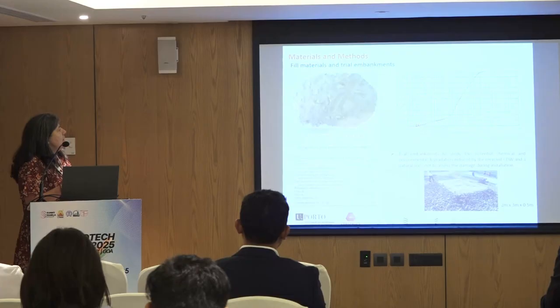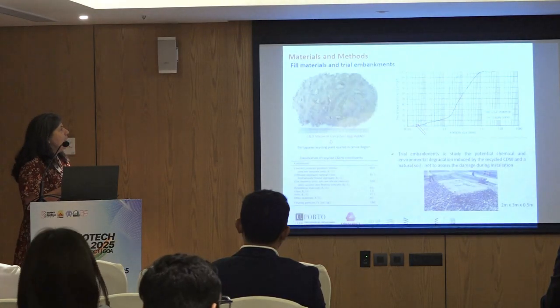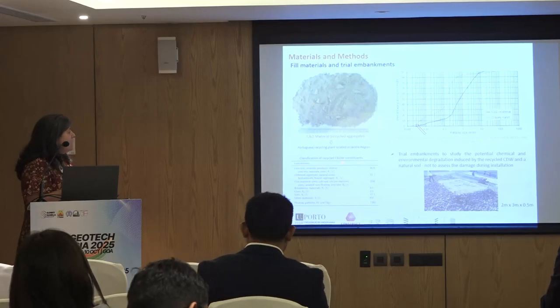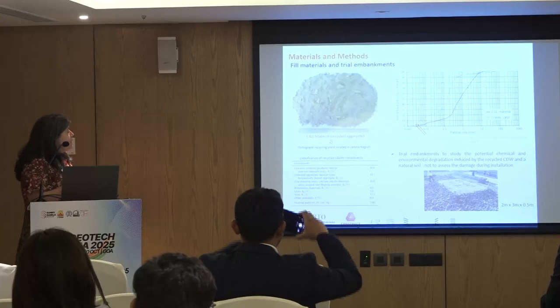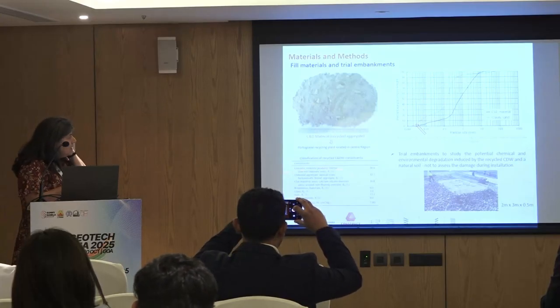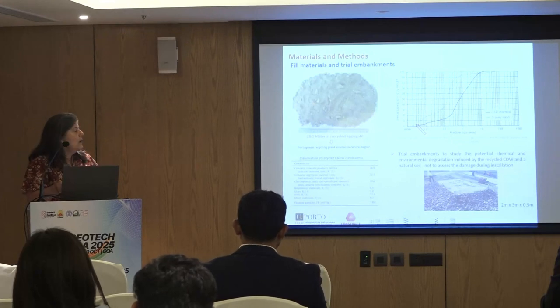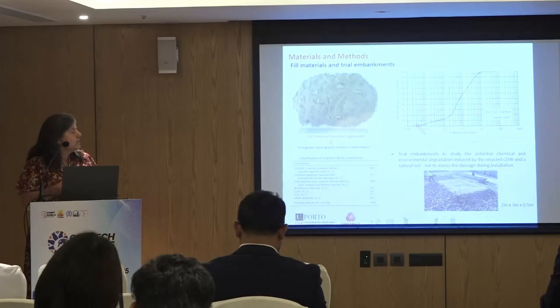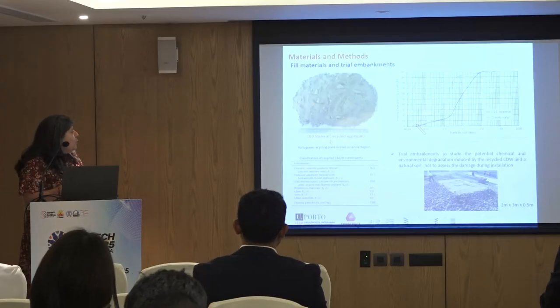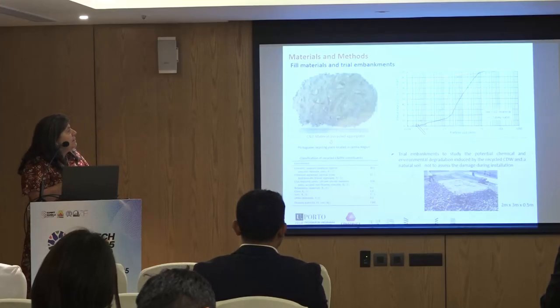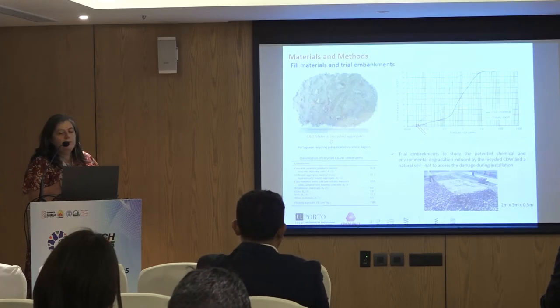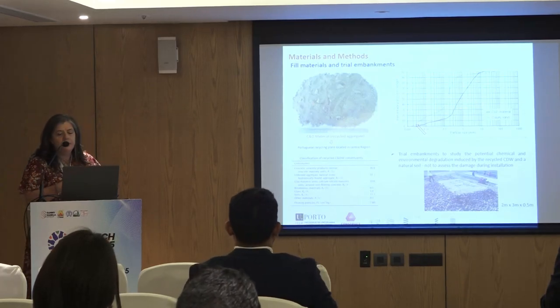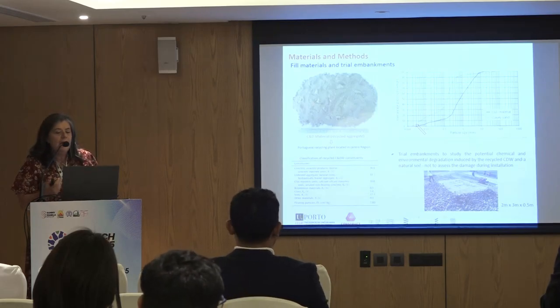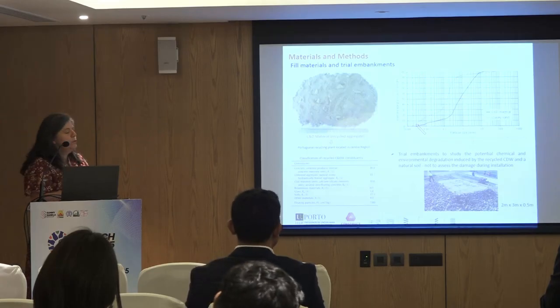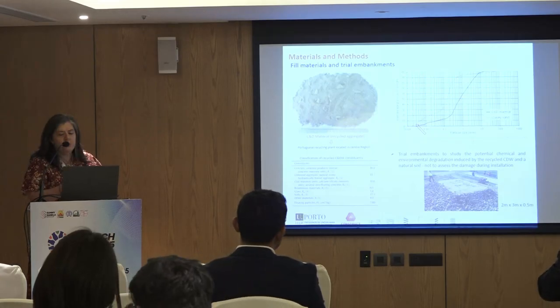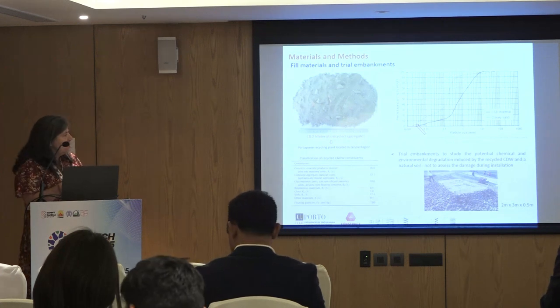So the recycled construction and demolition material is a fine-grained recycled material. The predominant constituents of this recycled material are, as you can see here in this table, concrete and mortars, unbound aggregates, natural stones, and also a significant portion of soil. In this graph, we show the particle size distribution. As you can see, the natural soil used in this study is finer than the recycled aggregate, and obviously is not a material typically used in the construction of geosynthetic reinforced structures due to its high fines content.